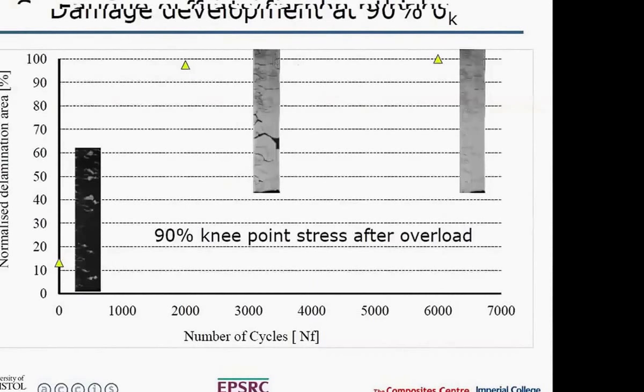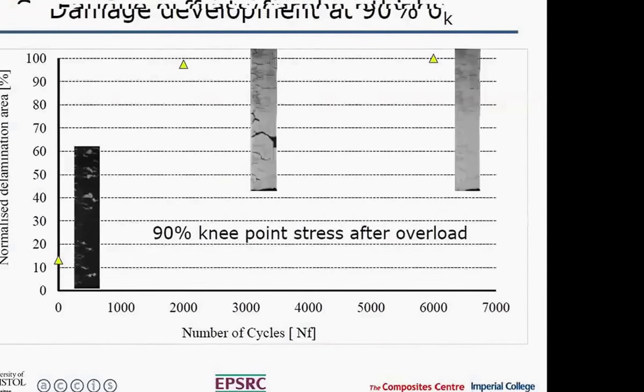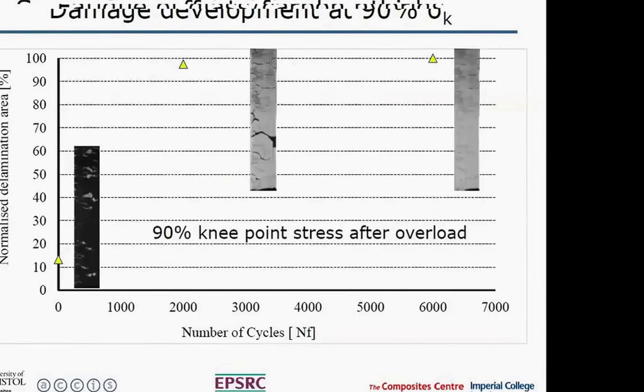And what you see is some delamination growing. This is at 90% of the knee point strength, so it's overloaded. Then we fatigue it at quite a high level, 90% of that knee point strain. You can see initially we've got a 12%. We measure the delaminated area using just the picture of it, the contrast between the delamination. So the initial overload produced about 12% change of area, so a little bit of delamination associated with these fragments. And then as we fatigue it at 90%, after a few thousand cycles, it delaminates.